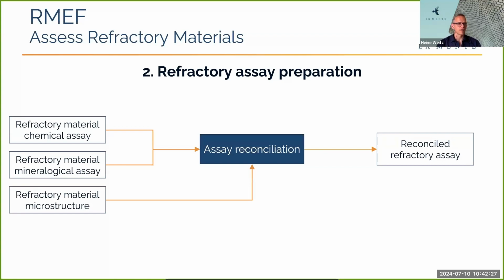One also needs to look at the refractory material microstructure. So using a technique like SEM-EDS to identify what the different minerals are in your refractory material. So it's not enough for the bulk material to perform well, but the individual phases also need to perform well. So if, for example, your matrix that holds your refractory grains together melts at low temperature, the refractory is not going to last.